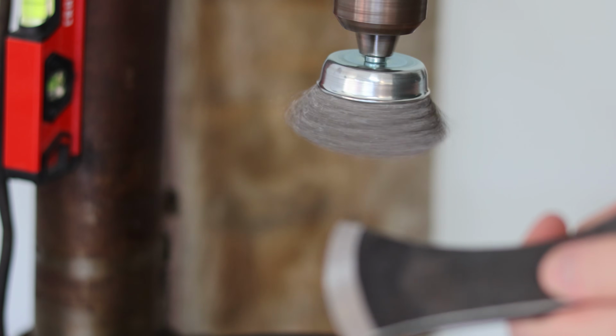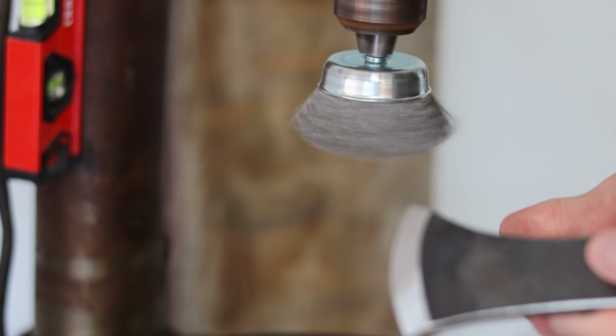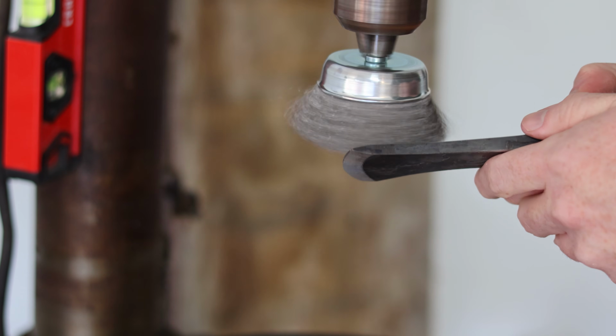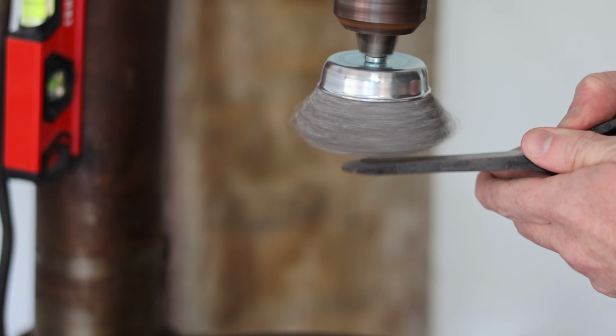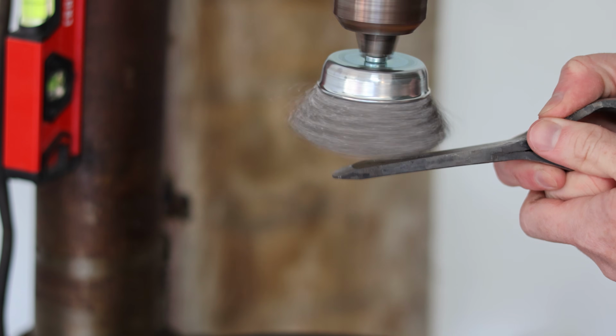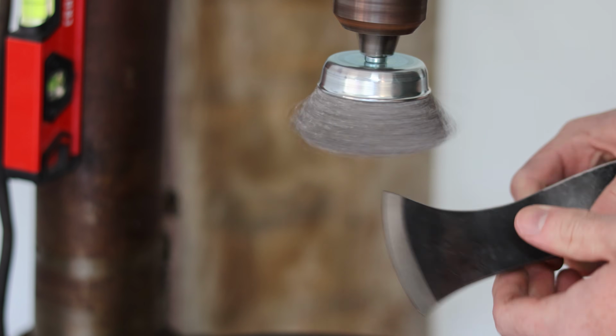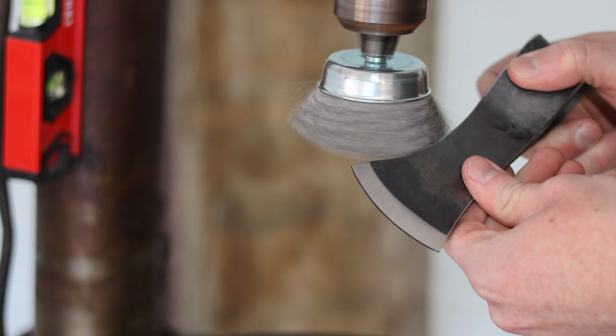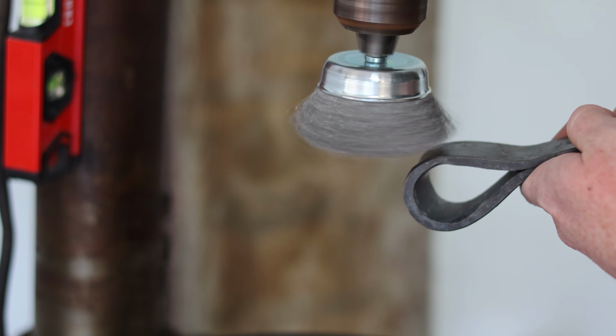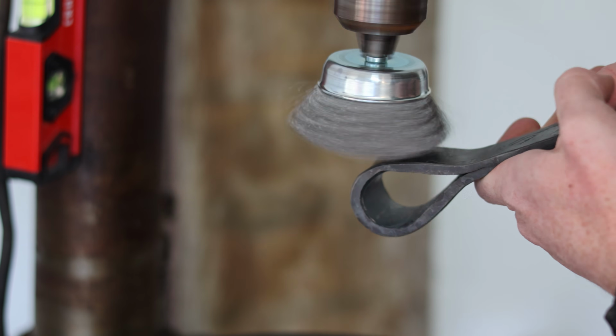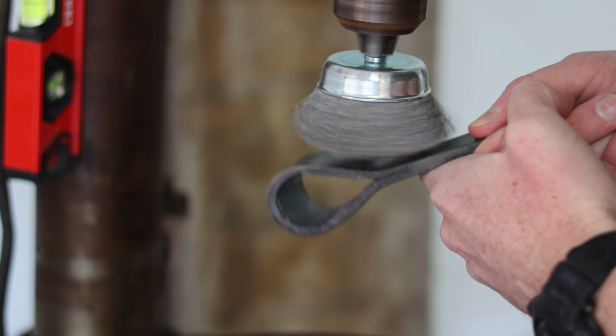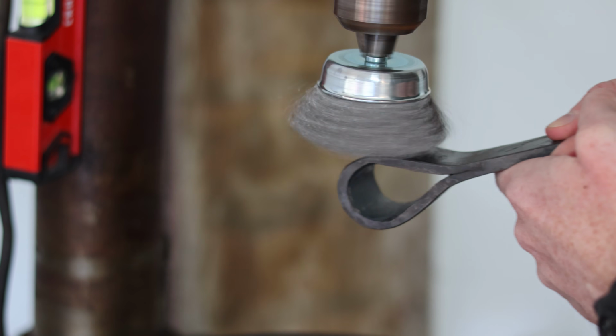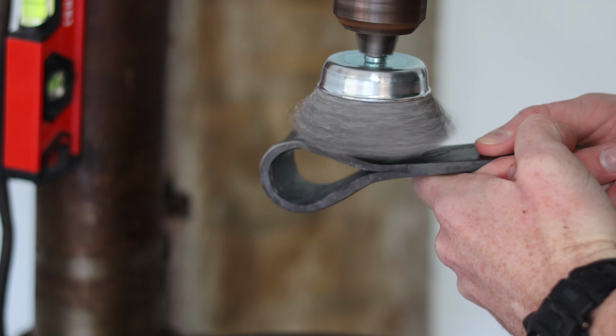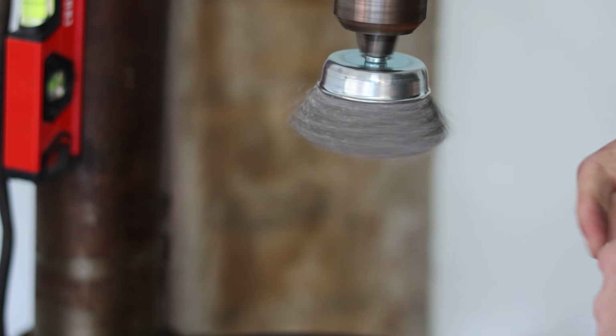And partway through grinding the bevels down, I remembered that I wanted to wire wheel this and kind of polish up the forge scale, make it look nice. And I'm glad I remembered when I did, because it's way better to do this before I put a sharp edge on this so that I'm not risking cutting myself. You can see me actually skipping off the wire wheel a couple of times here. That would have been pretty nasty if that blade was sharp. If you were making a knife or a tomahawk or a hatchet or anything of that nature, make sure you're getting things done before you actually sharpen as much as possible.